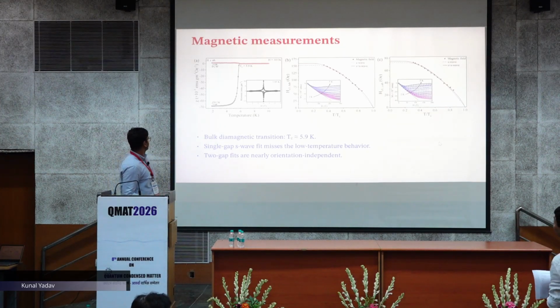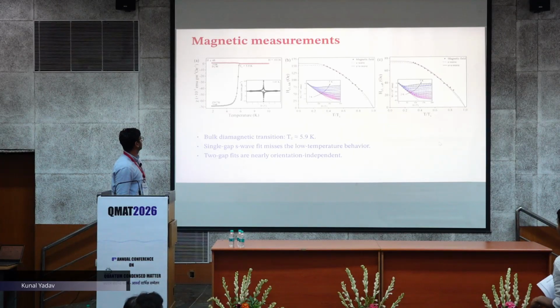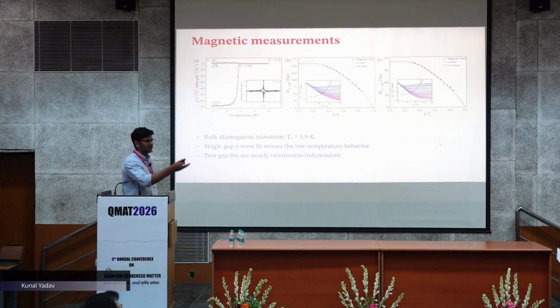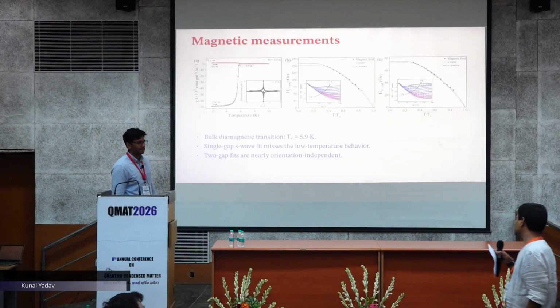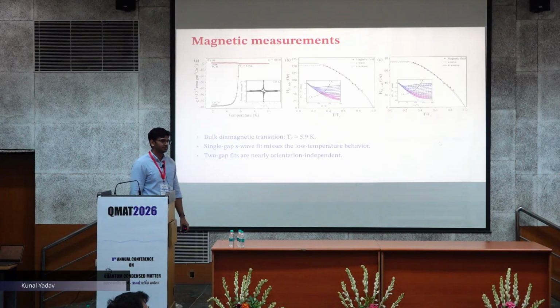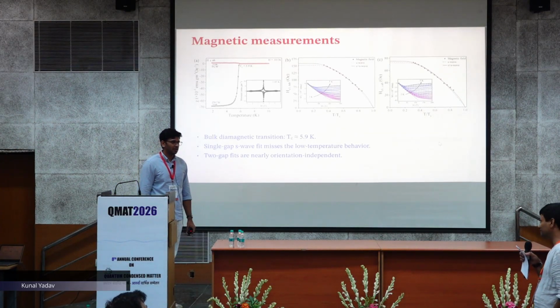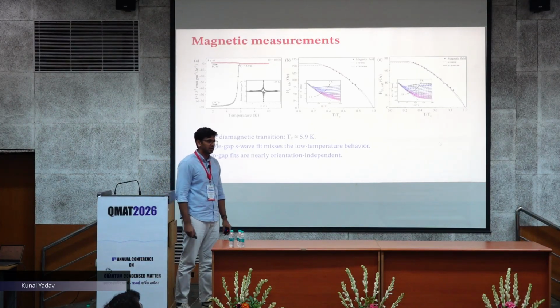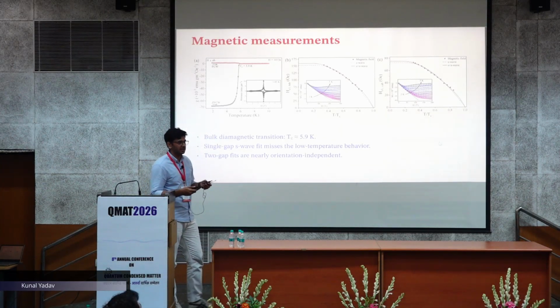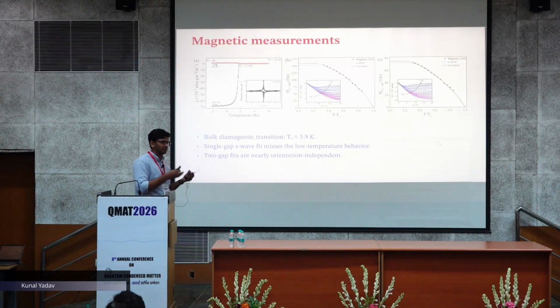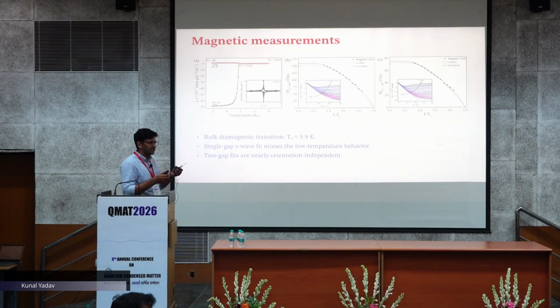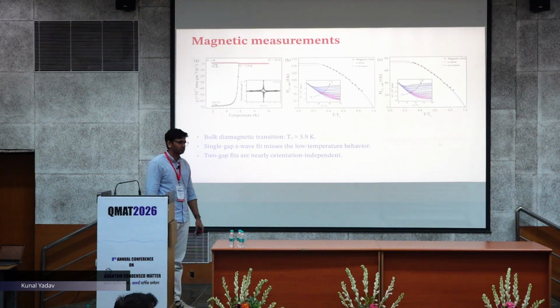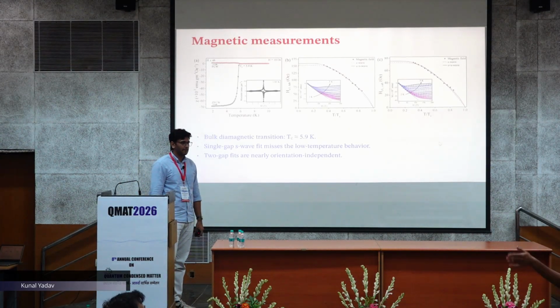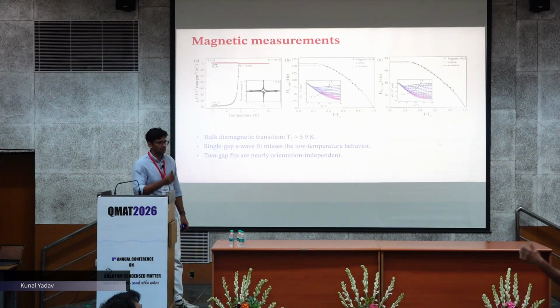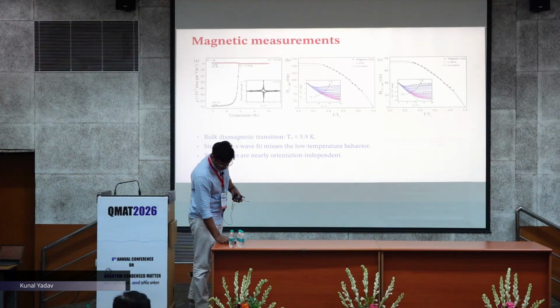This is not a volume fraction of your 4 pi chi. And so your conclusion is that charge density wave is not responsible for the multiband. Yes. But why did you think that it should? There are some papers in Science that claim that the CDW is mimicking the multiband superconductivity, the signatures of multiband in NbSe2, at 30 Kelvin, 40 Kelvin CDW, and how it is affecting the multiband superconductor. Okay, we can discuss. Yeah, okay, thanks. Sure. Okay.